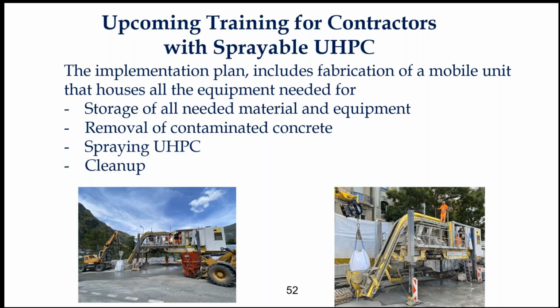It's going to have hydro demolition equipment in there that you can take into the field to remove the contaminated concrete to the extent that you want. And then it's going to have the silos to store most of the material. Most likely we just have to bring the sand on site using a local material. But things like silica fume, slag, superplasticizer, and admixtures for the spray, and the water, are going to be housed in the silos in the unit.